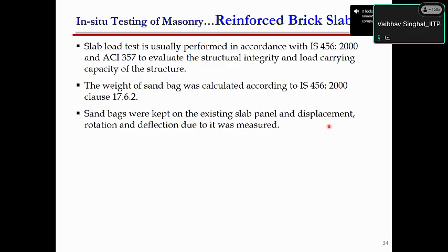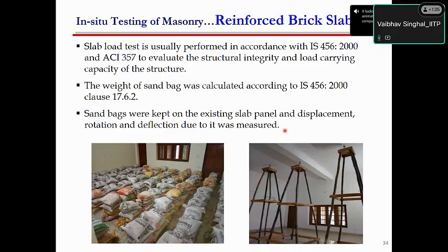Okay, so another test which can be done for the slab is the slab load test. It can be done as per IS 456, or you can also refer to ACI 357. In this test, simply sandbags are kept over the existing slab. So this is a picture, where sandbags were used to load the slab, and then you can put deflectometers or displacement gauges from the bottom, and you can find out how much is the deformation, how much is the displacement.